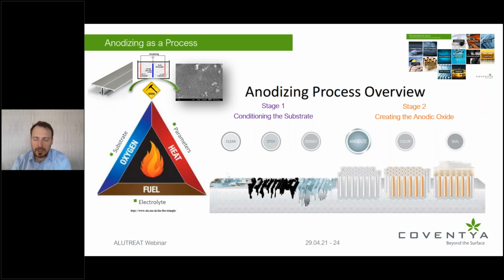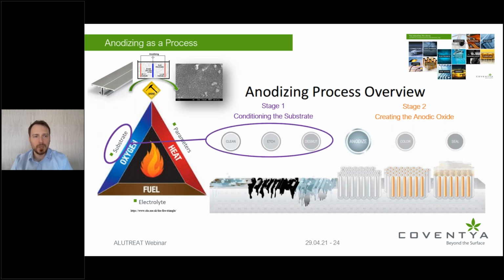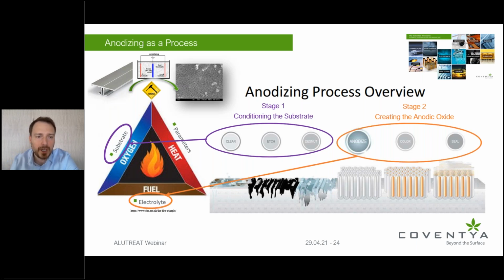So this is a principle that we have started to take from plating, that we are not just concentrating on individual processes, but on the general sum of the process. We are not supplying our chemistries just to adjust the surface in aesthetical means, meaning adjusting the surface gloss, but rather to adjust the substrate, which enables our customers to have a much more suitable base material for the subsequent operations, where they can adjust the electrolyte parameters and get a good anodizing or color and even the seal.